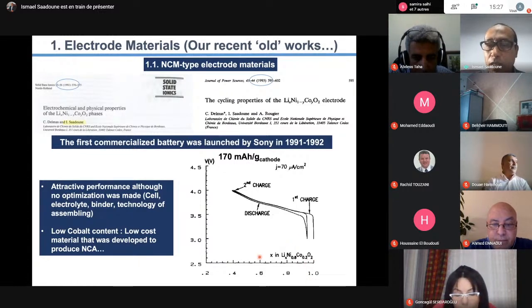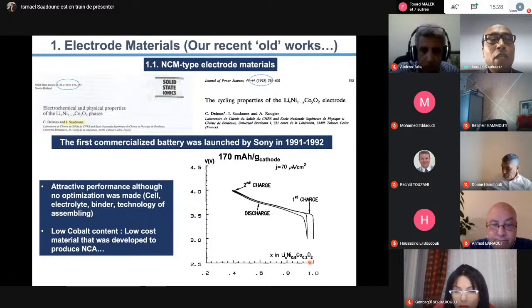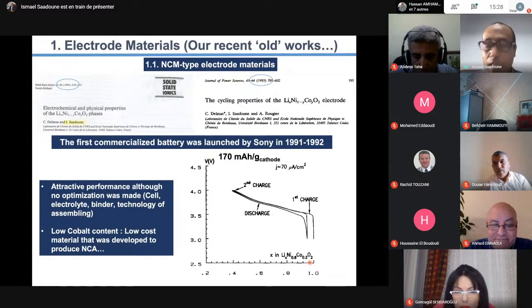This material, published in 1992, was used as the starting material to prepare NCA, because NCA is that material where we remove 5%, 0.5 cobalt, and replace it with aluminum. So I'm so happy to see that, but I think at that time we could have been rich if we'd decided to patent instead of publish.